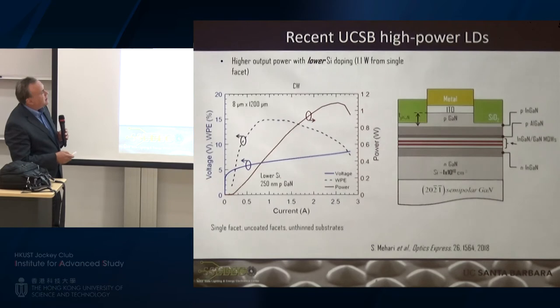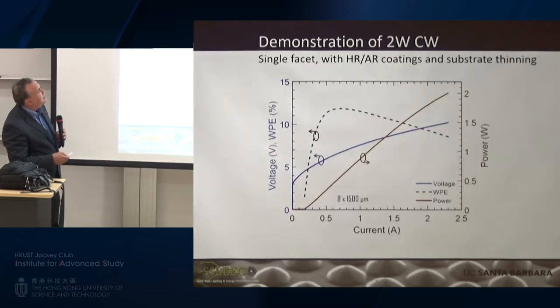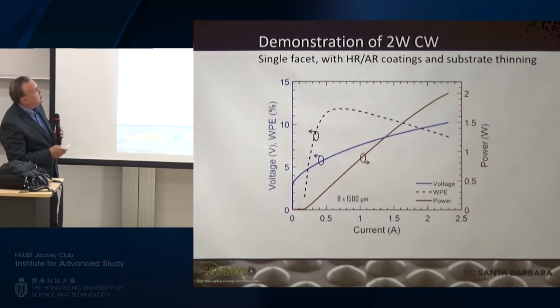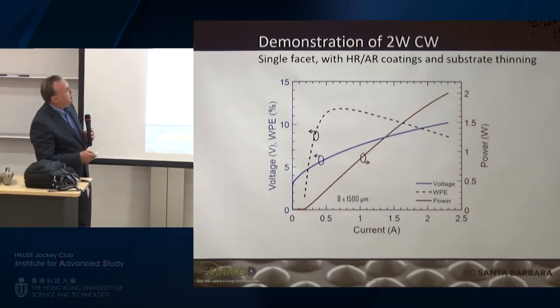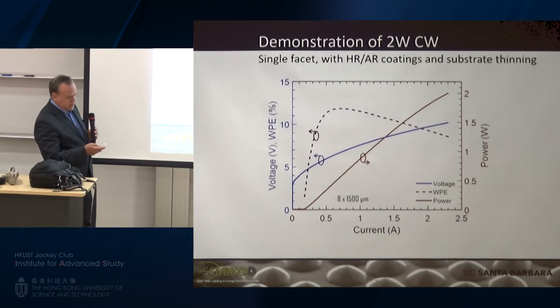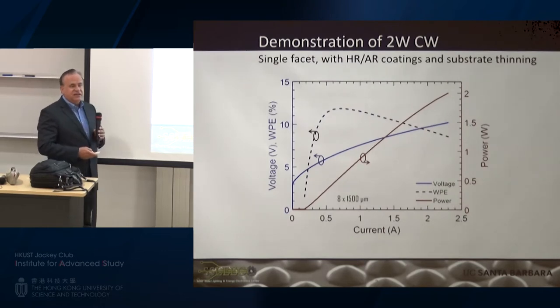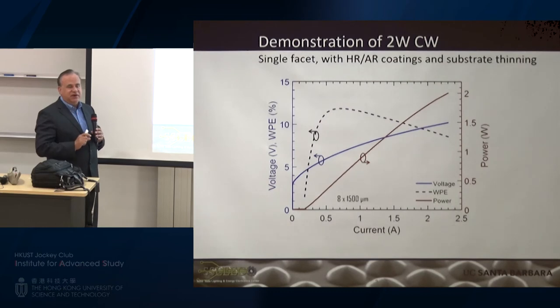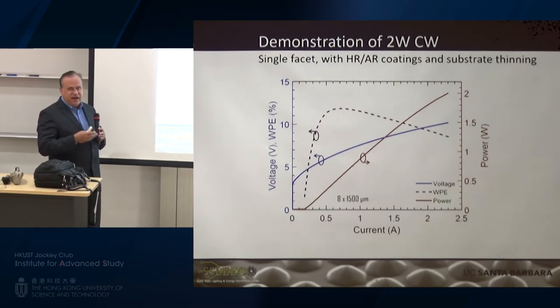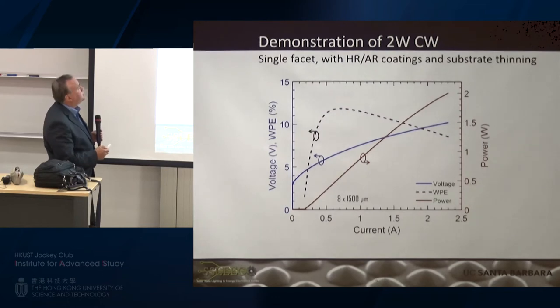The other thing is we found out the loss was coming from the facets. So if you coat the same material with an HR coating, in this case tantalum pentoxide and silicon dioxide, we were able to get up to 2 watts from a single substrate. This is important because 2 watts gives you enough power to make a 40-watt light bulb. Again, this is 0.3 millimeters of material, so I can get 40,000 light bulbs from a single 2-inch wafer. And Kimmy knows they have reactors that can grow 50,000 light bulbs a day from a single reactor.